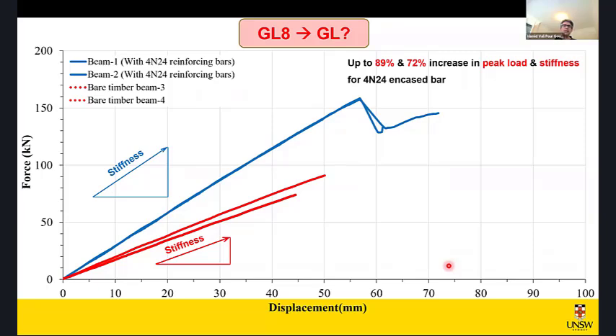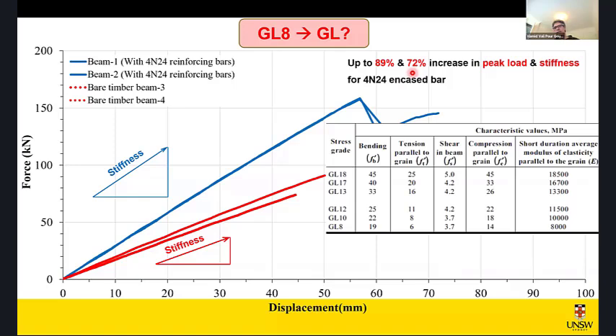Now, let me just explain in simple terms what that improvement means, if you want to see what the performance of this new reinforced cross-section is like, and it's on par with what GL grade. Keep those two numbers just in mind, 89% and 72%. Now, I took this table, which is table 7.1 in AS 1720, and look at this table. The beam initially we picked up was GL8. The bending strength, of course, the characteristic value is 19, and elastic modulus is 8,000, all right? Now, let's multiply this bending strength by 1.89, which is 89% improvement in peak load.